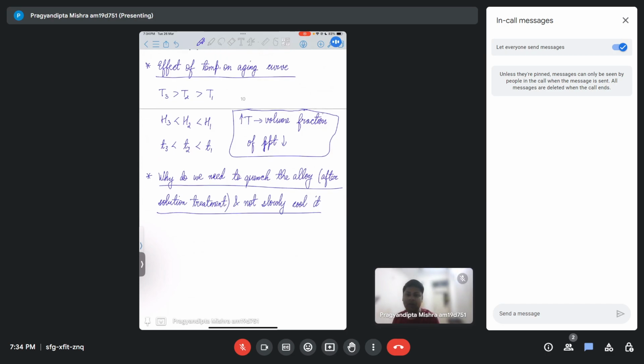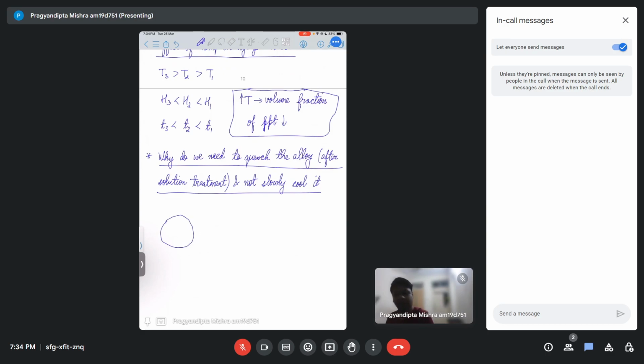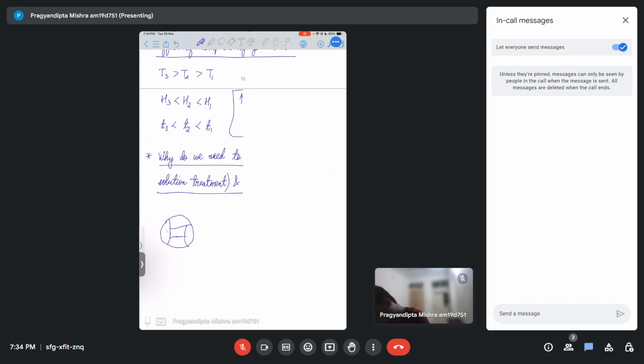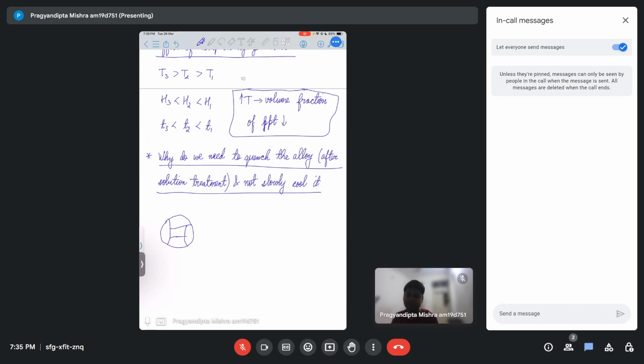Essentially, what happens is, if we allow it to slowly cool, right? So supposedly this is my entire matrix, okay, and I'm allowing it to slowly cool. So what will happen is the precipitate would tend to form at regions where it is easy for the precipitate to form, right? So most of the precipitate will start forming around the grain boundary, in the grain boundary region. They'll start concentrating around the grain boundary. Okay.